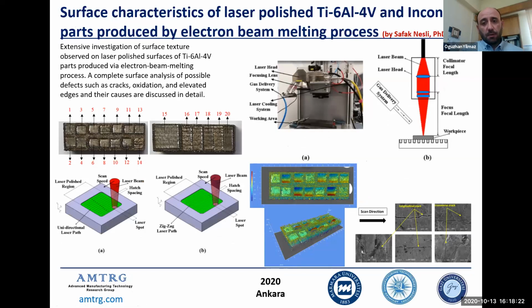And we do some research mainly on the post-processing of additively manufactured parts, because we know that the parts have very poor surfaces. The surface roughness is very bad, so we need to remove it or improve it. So we have an experimental laser beam machine, and we do laser polishing processes. Laser polishing is a known process, but we apply it especially to EBM surfaces made of titanium 6-4 and Inconel. This is a research project supervised by me and Yusuf Kaynak at Marmara University.